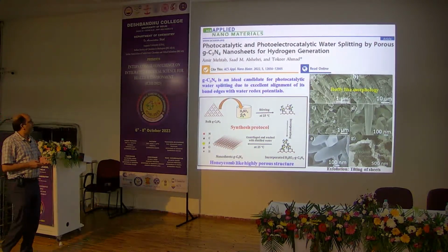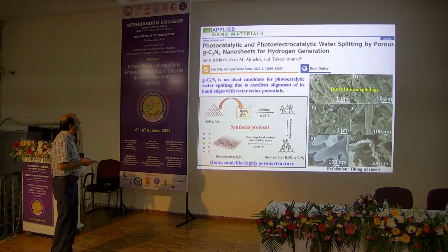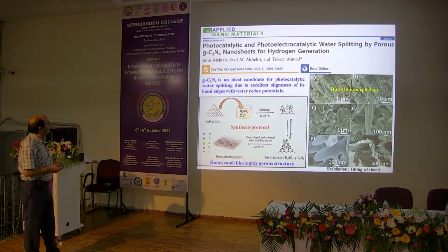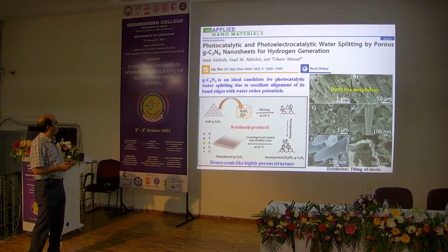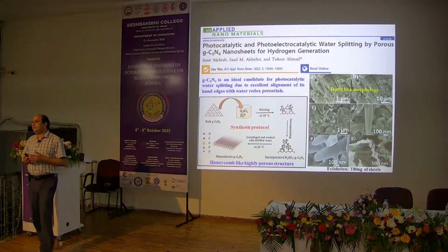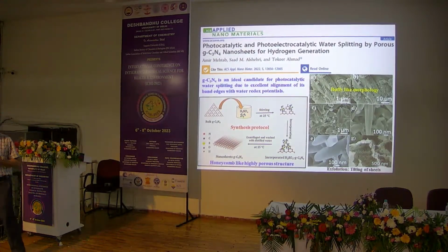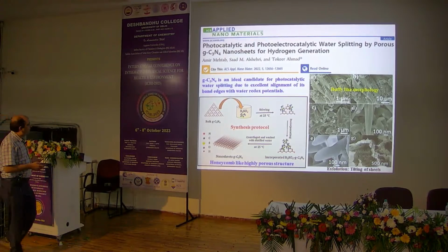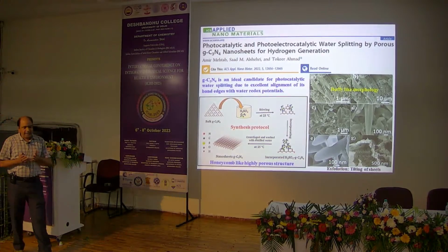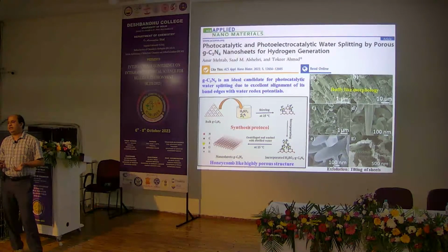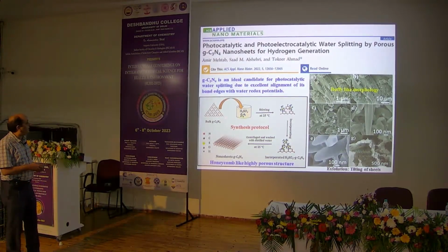The reason is that GCN is an ideal candidate for photocatalytic water splitting due to excellent alignment of the band edges with the water redox reaction, and the synthesis is also very simple. If you take melamine and heat it at around 520 degrees centigrade, you will get the bulk graphitic carbon nitride.